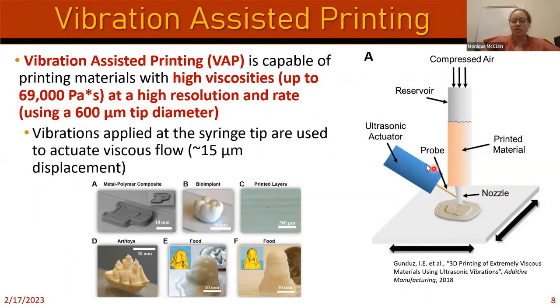So we decided, let's try developing this new method, vibration-assisted printing. Basically, this part here is very similar to normal direct ink write, where you have your material in a syringe and some way to push that out of a tiny nozzle, right? We use compressed air, but you could use a motor plunger system, for example. But the key thing that we did differently is that at the tip here, we added an ultrasonic probe that applied vibrations at the tip of the nozzle. What those vibrations did for us was allow us to deposit this material much faster. It could be a much more viscous material than when we just did direct ink write. And typically the nozzle exit diameter would be smaller than if it was pure direct ink write, where we just push the material out.